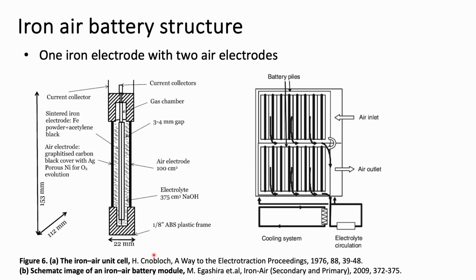To compensate for the sluggish rate of oxygen reduction, the batteries usually consist of one iron electrode with two air-breathing electrodes on each side in a plane parallel configuration. Also, most battery systems having an iron anode often suffer from a large amount of heat evolution due to its large overpotential during long-term usage. Such heat dissipation can be inhibited by the circulation of the electrolyte and an auxiliary pump cooler system.